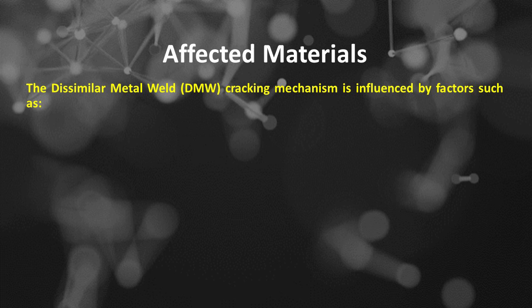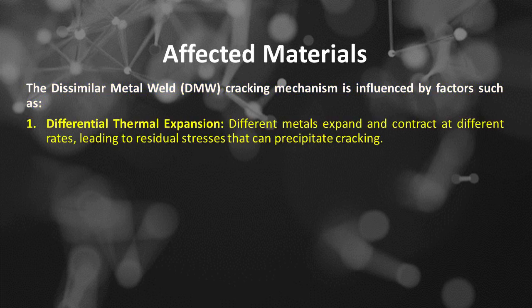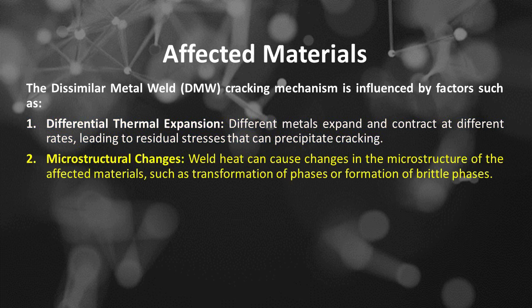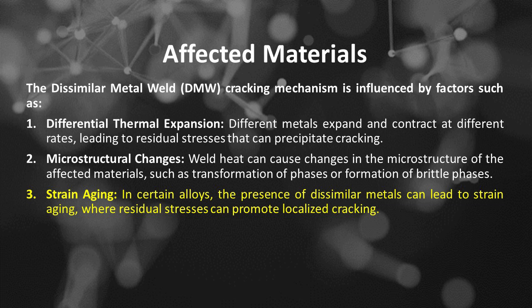The dissimilar metal weld, or DMW, cracking mechanism is influenced by factors such as: Number 1 is differential thermal expansion. Different metals expand and contract at different rates, leading to residual stresses that can precipitate cracking. Number 2 is microstructural changes. Weld heat can cause changes in the microstructure of the affected materials, such as transformation of phases or formation of brittle phases. Number 3 is strain aging. In certain alloys, the presence of dissimilar metals can lead to strain aging, where residual stresses can promote localized cracking.